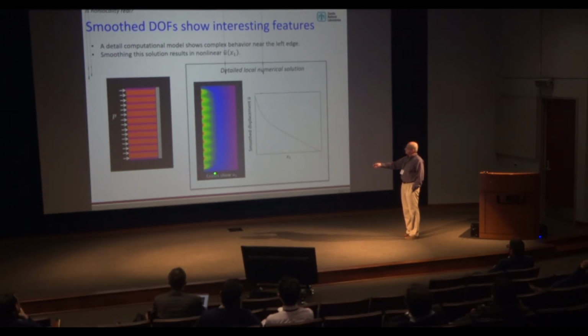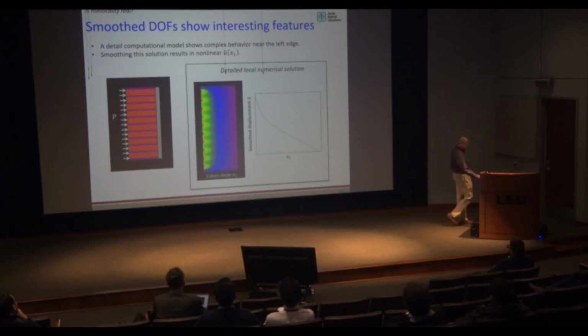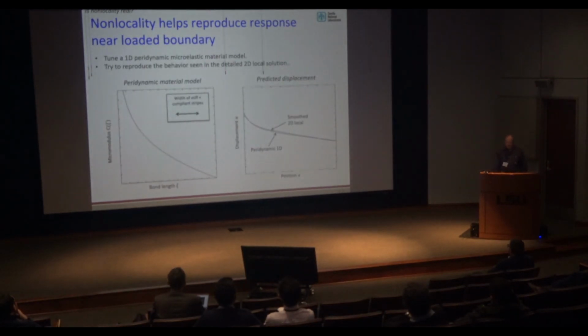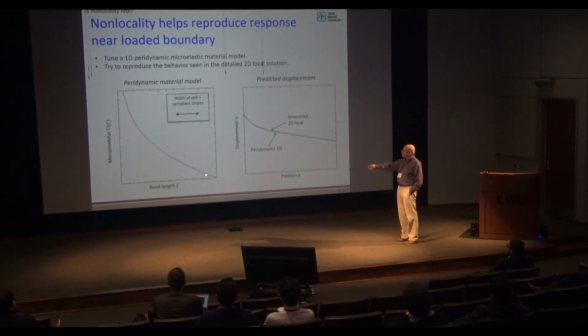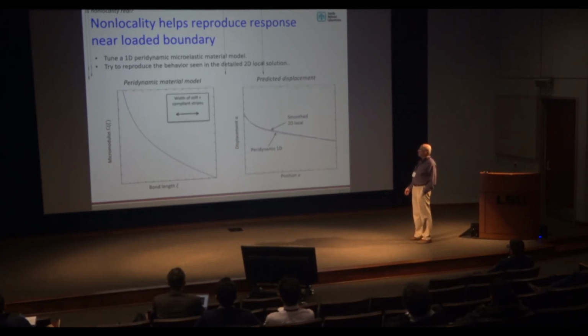So if you do that detailed 2D calculation and then average the displacements along vertical lines, out here you still get the local result that we looked at in the Dirichlet problem, but near the edge, the smooth displacements have this nonlinear feature. So what's up with that, and how can we represent that in a 1D model of this problem? Well, I spent some time just playing around with different micromodulus functions in a 1D peridynamic model, which are not a function of position. They're the same everywhere, trying to optimize the agreement with this detailed but smooth solution that I was just talking about.